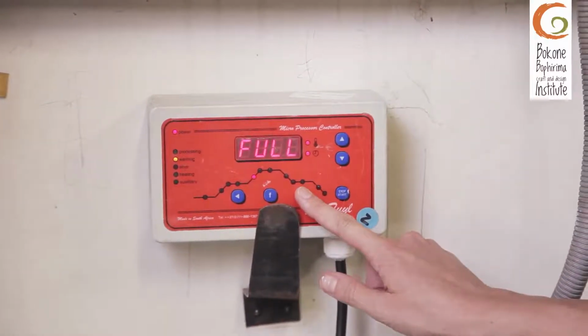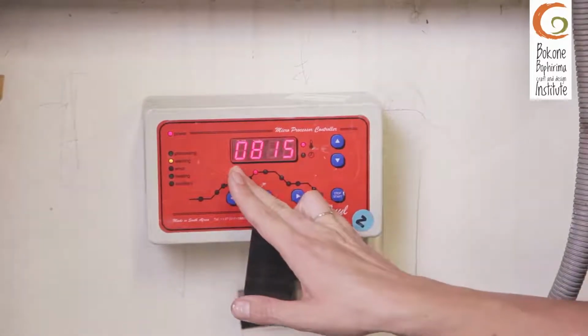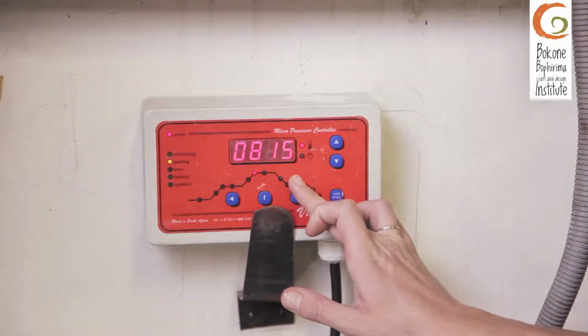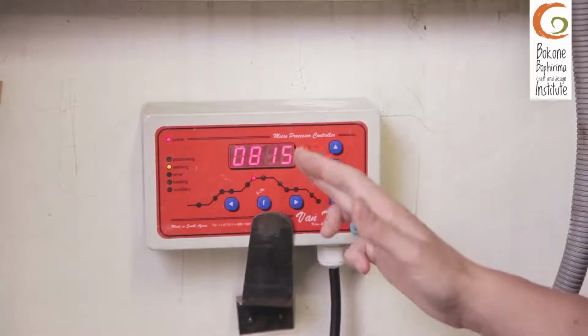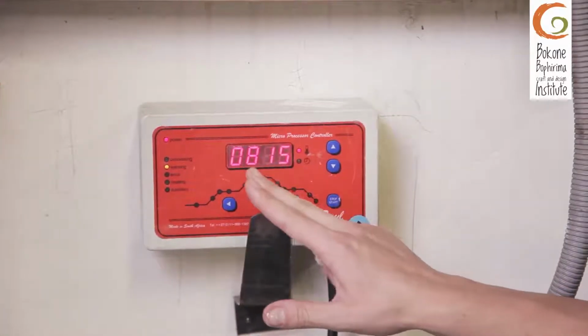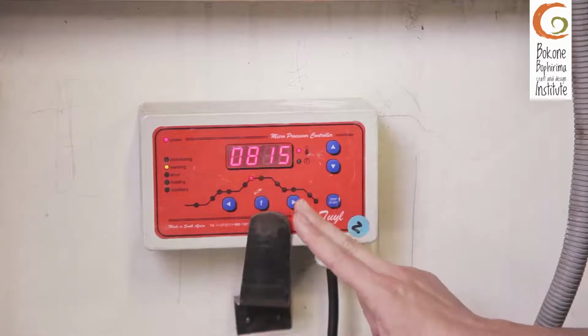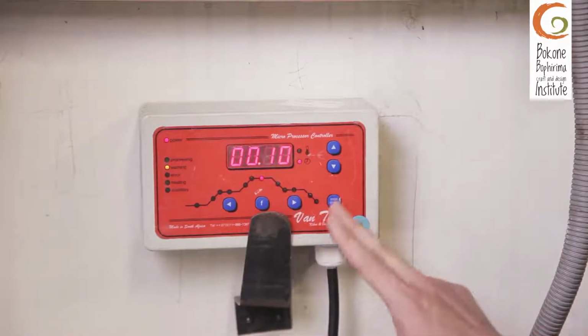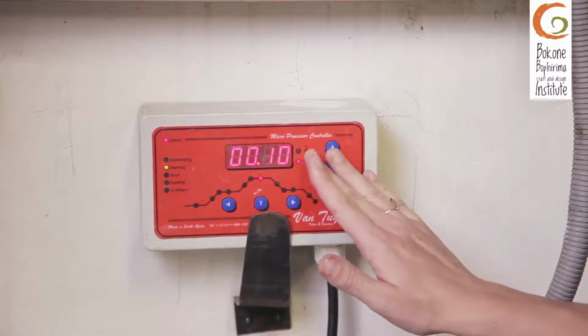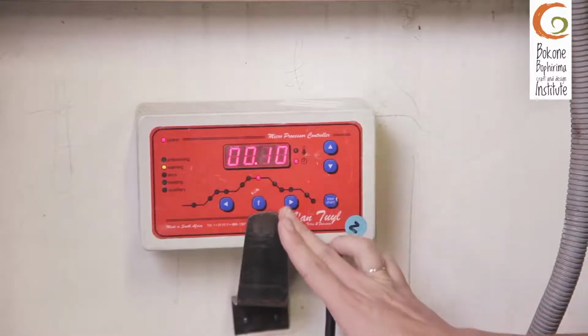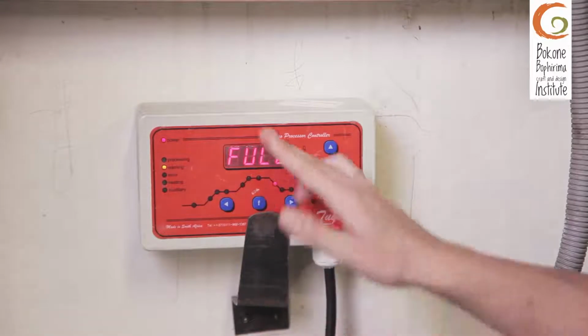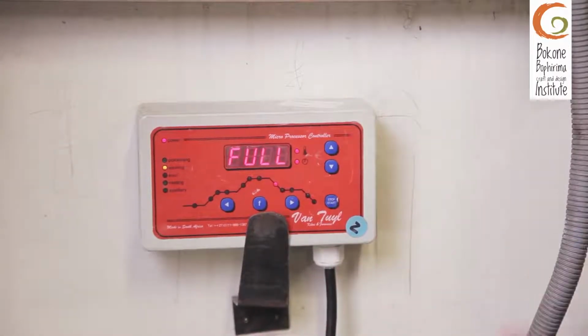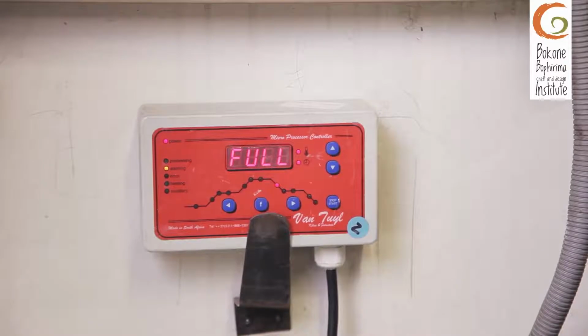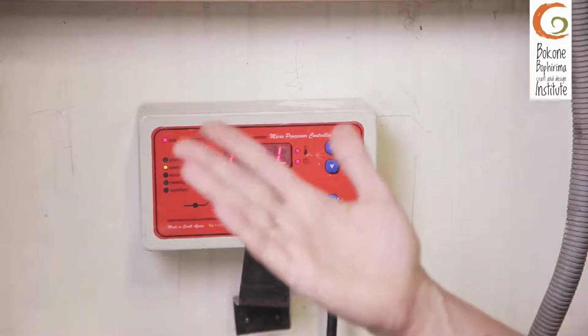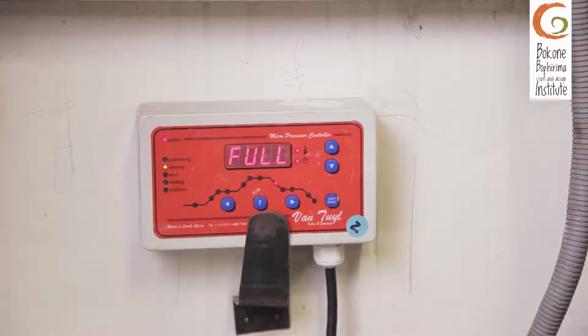So I want my glass to go as fast as possible up to my top temperature, where I'm working with 815, which is according to my test pieces, my desired top temperature for my high temp enamel paints. I'm then going to allow it to soak for 10 minutes. 10 minutes is sufficient for this firing, and then I need to now crash cool. So now I'm not physically going to crash cool, which one can also do. You can assist the kiln by opening up the lid and crash cooling the kiln down to 680 if you're going to manually do it.